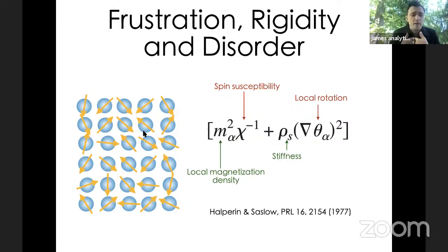And so by solving the free energy, they discovered there are these hydrodynamic modes, which are effectively the equivalent of the magnon in the ferromagnet. The result is that these kinds of collective modes can actually transport angular momentum. They can actually transport spin, even though the system is not in a kind of equilibrium state that we understand very well, like a ferromagnet or an antiferromagnet. As far as I know, though, no one's seen really clear evidence of the existence of these modes, although there have been some indications that they might be there.